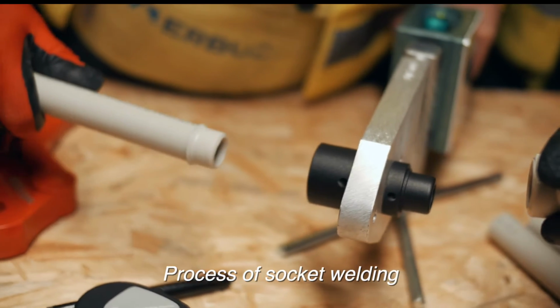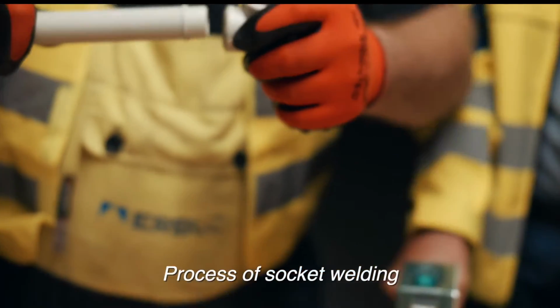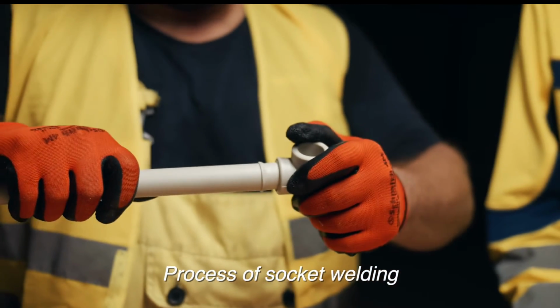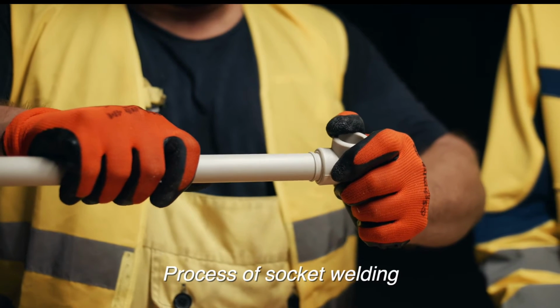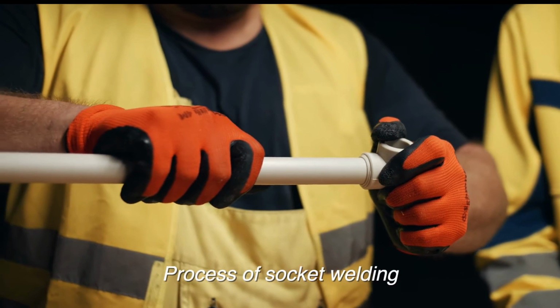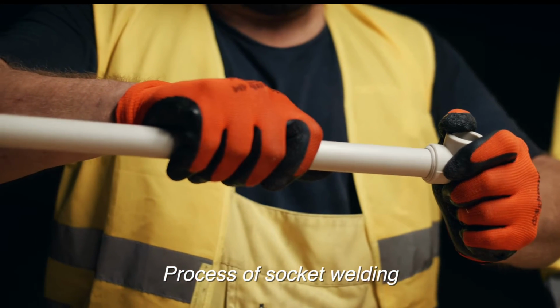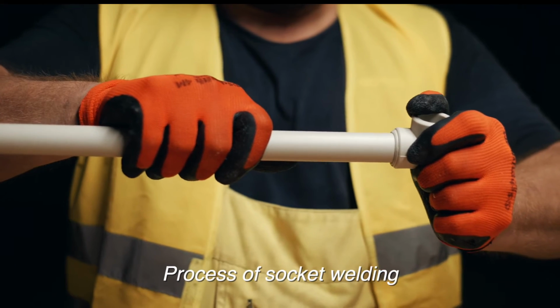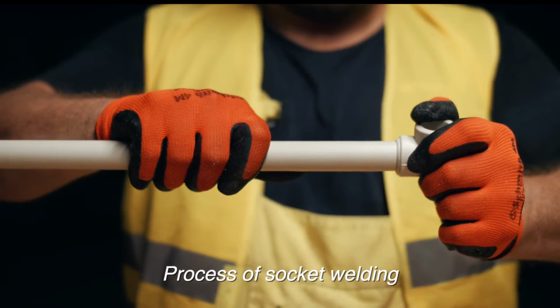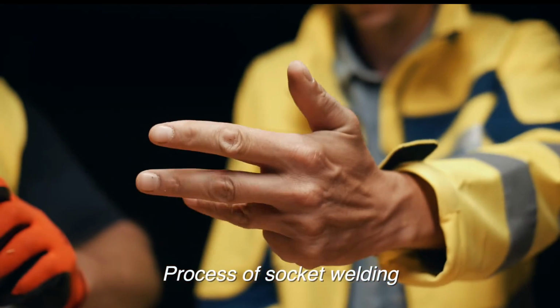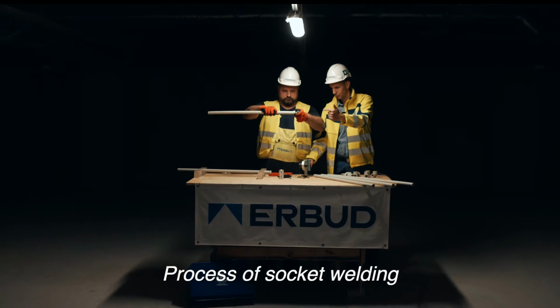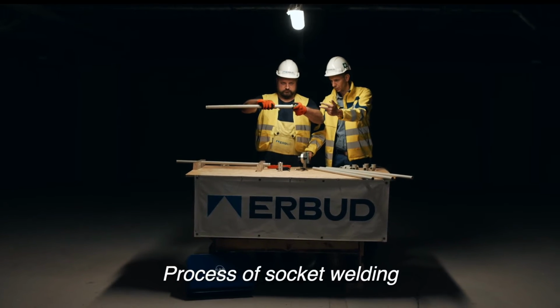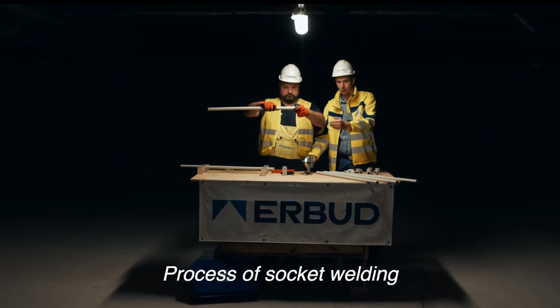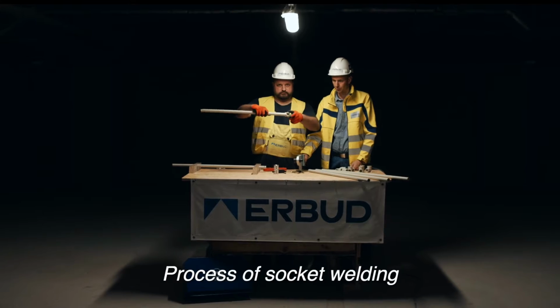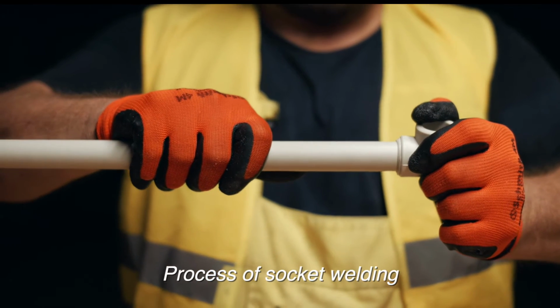After heating time has elapsed, remove the pipe and the fitting from the heating pins at a steady pace and connect them immediately without turning them by inserting the pipe into the fitting until the marked line of the welding depth is covered by the excess material known as the flash. Do not surpass the welding depth, as a narrowing may form in the connection point, and in extreme situations the pipe may even become completely blocked.